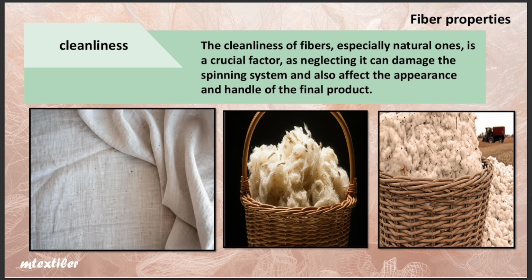For wool and silk fibers, protein-based grease can be very problematic, as these substances can prevent dyes and other necessary materials from penetrating the fibers. Therefore, we must use certain chemical and physical cleaning methods, but they can also cause problems for the fiber structure. Chemical cleaners can expose the fiber to degradation and make it unspinnable. Physical cleaning, which removes impurities from fiber bales, can result in the loss of healthy fibers along with the impurities.